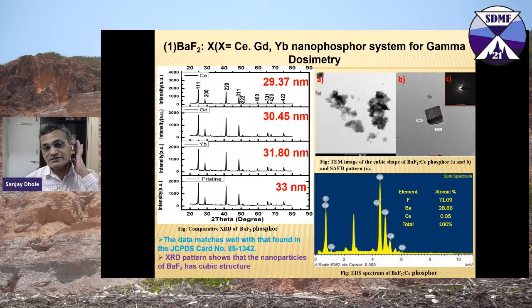Now, once you synthesize the nanophosphors, the first characterization to be performed is structural, to know the structure and the morphology. The structure we can come to know through XRD, X-ray diffraction. Here, this is barium fluoride doped with cerium, gadolinium, and ytterbium, and we are using this particular system for gamma dosimetry.